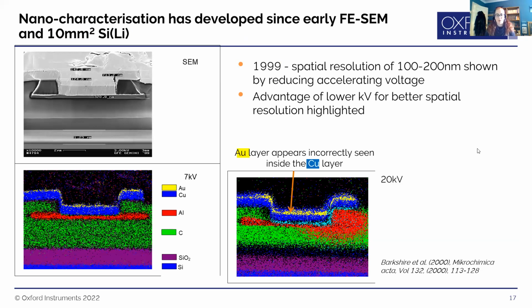And this problem of having a large volume signal and being able to resolve small features has been acknowledged for quite a long time. So this paper was produced in 2000, and it was looking at the spatial resolution using EDS. And you can see here with 7 kV, you've got much better differentiation between the layers than you do at the 20 kV.